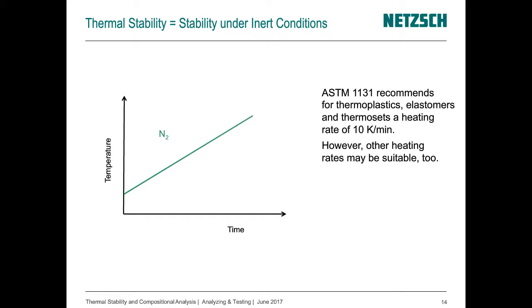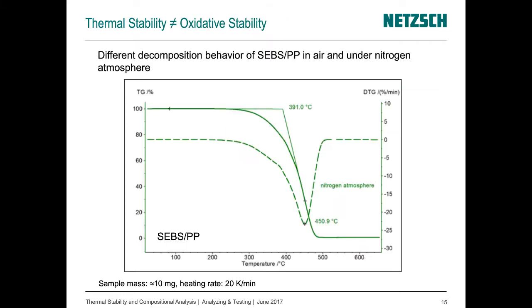In this slide and in this example, I will show you the difference between the thermal stability and the oxidative stability. We see here in green the thermal behavior of a SEBS PP sample. PP stands for polypropylene and SEBS stands for styrenic block polymer with the components styrene, ethylene, butylene, and styrene again. And if we heat this material in nitrogen atmosphere, then we get a decomposition which starts at about 300 degrees C and ends at about 500 and a little bit. The main peak in the DTG curve, so in the derivative, is at about 451 degrees C.